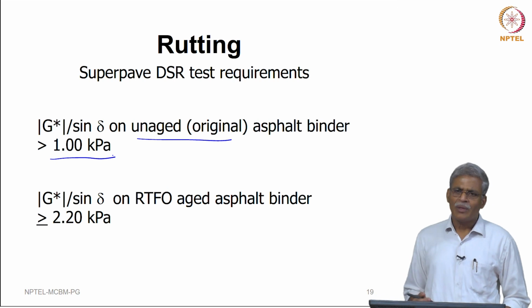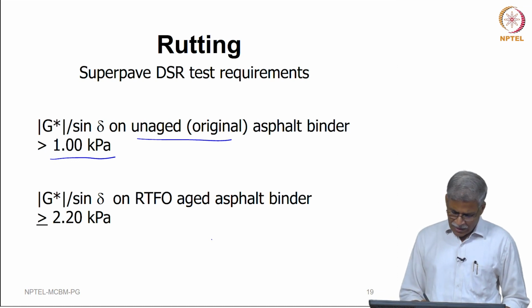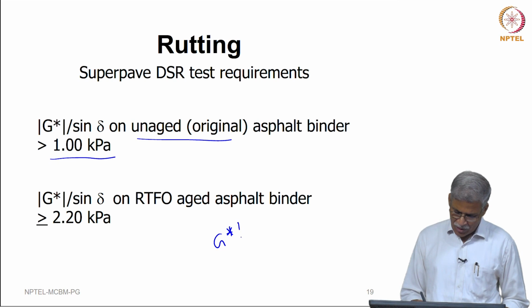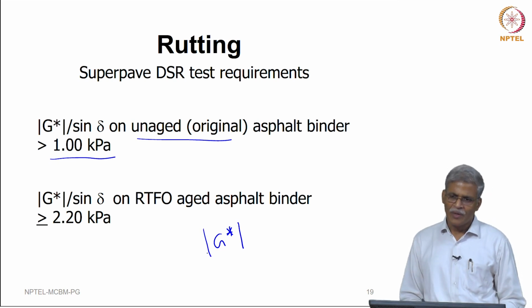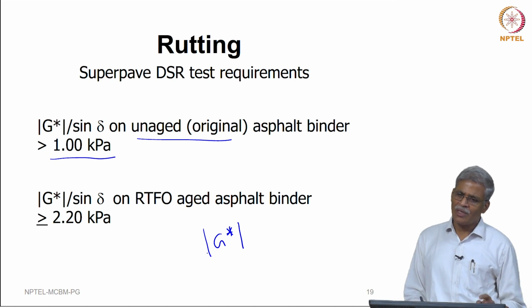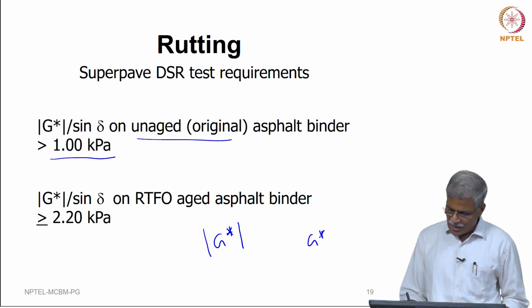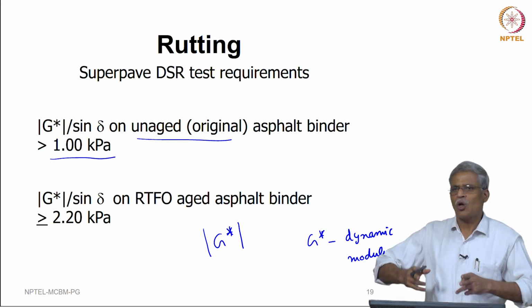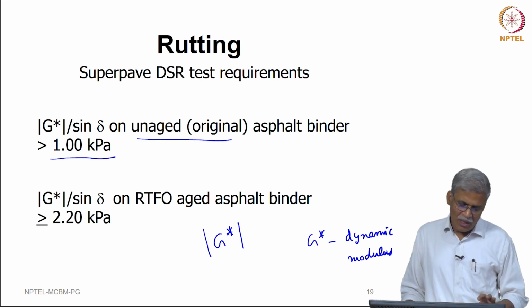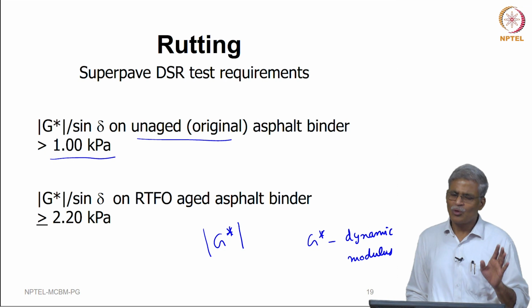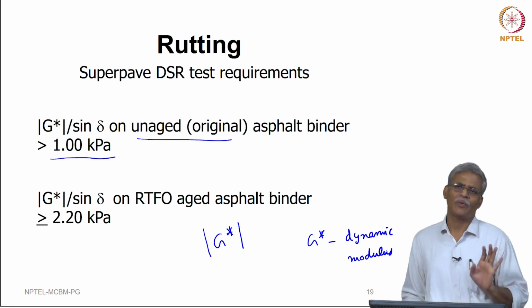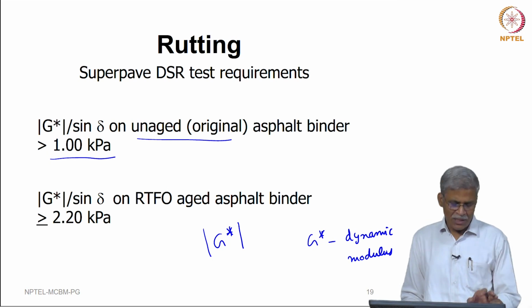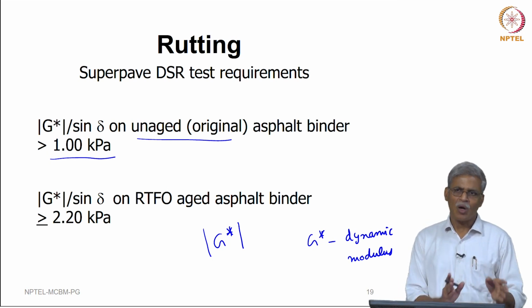There is a caution that I need to exercise here as far as this specification is concerned. Normally, in most of the ASTM as well as AASHTO specifications as well as in published literature, G star is written as it is without these two vertical lines around it. What ASTM or AASHTO specifically means when they write G star is only the dynamic modulus, which is the mod value of the complex number. For convenience, they have just dropped these two vertical lines surrounding it, but I have introduced them here again so that at least the students here will understand that this is the correct way of writing. If you read the European specifications, they are always written as the mod value of the complex modulus.